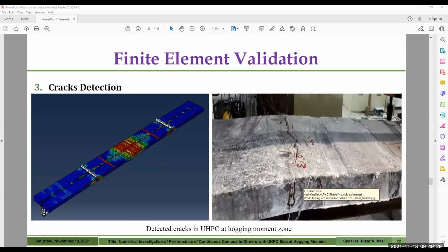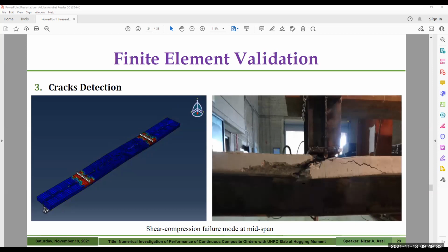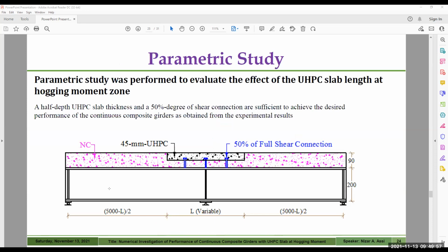The model also detects the mode of failure, the shear compression mode of failure, which took place at the mid span in the concrete, shear compression failure within the concrete at the mid span. So on both spans, because we have symmetry in the specimen. So we can conclude that this model is validated and it can be used to predict the effect of new parameters which were not tested experimentally.